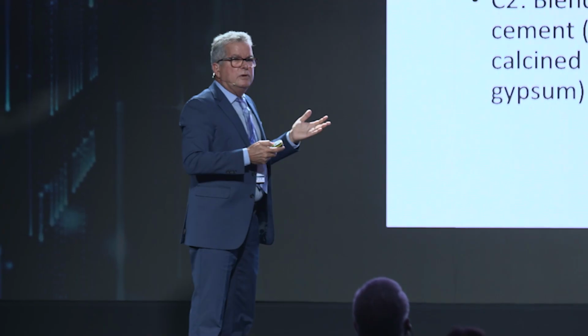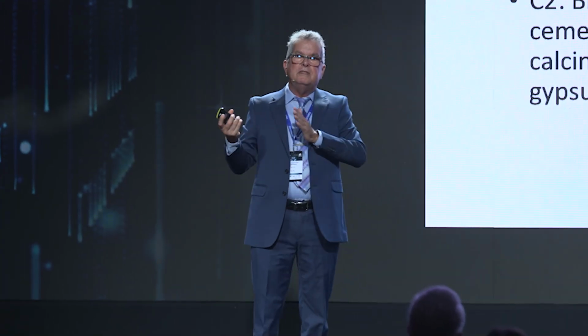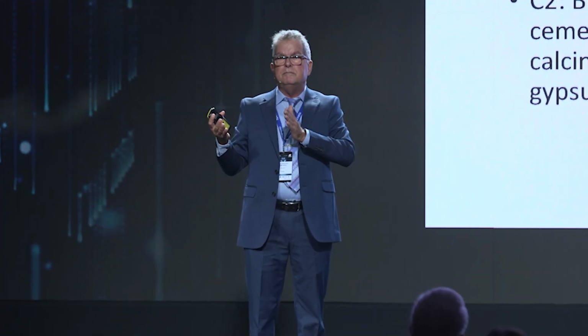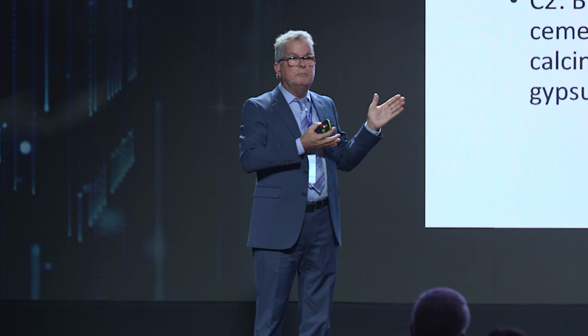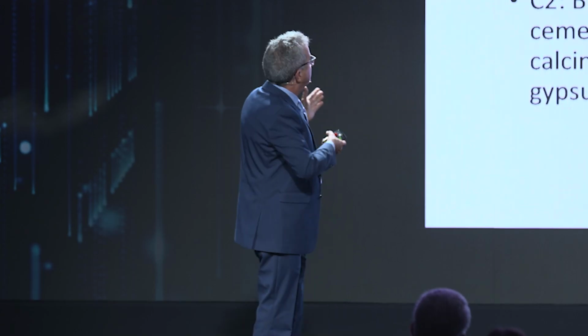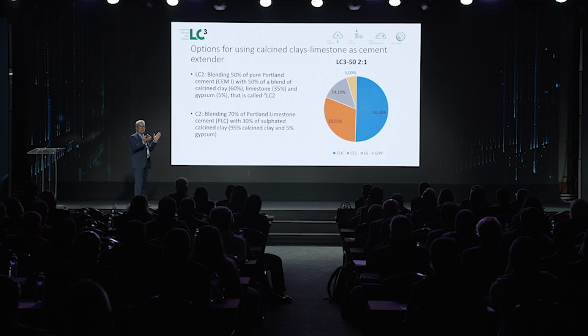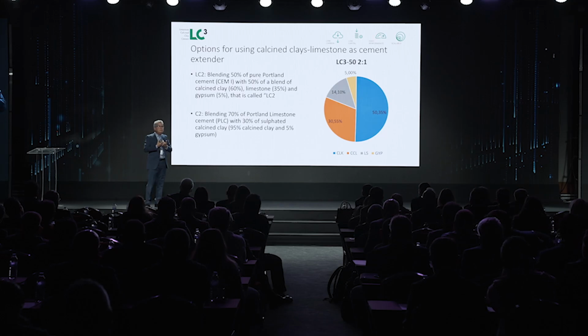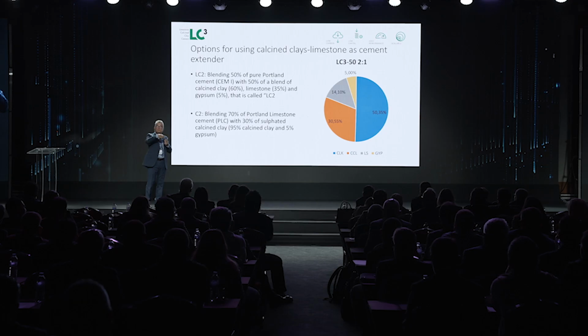And the other thing that we're doing more and more, especially for the ready-mix industry, is instead of producing a cement, we're doing a separate grinding, and we're producing mineral additions. Either what we call LC2, which is blending 60% of calcined clay, 35% limestone, and 5% gypsum. Gypsum, people always ask, why gypsum? Because you need to sulfate the system. Because of the high specific surface, there's a boost on the hydration of the product, so you need to put more gypsum in the system. You put it automatically there.